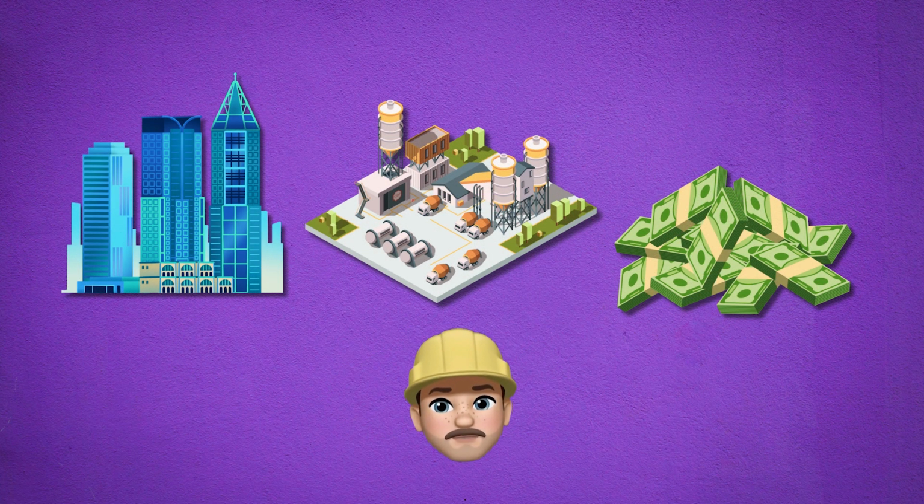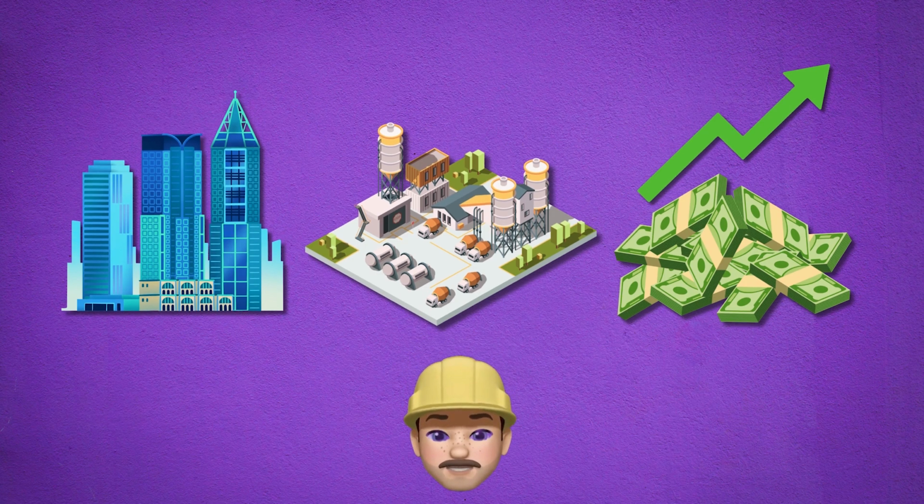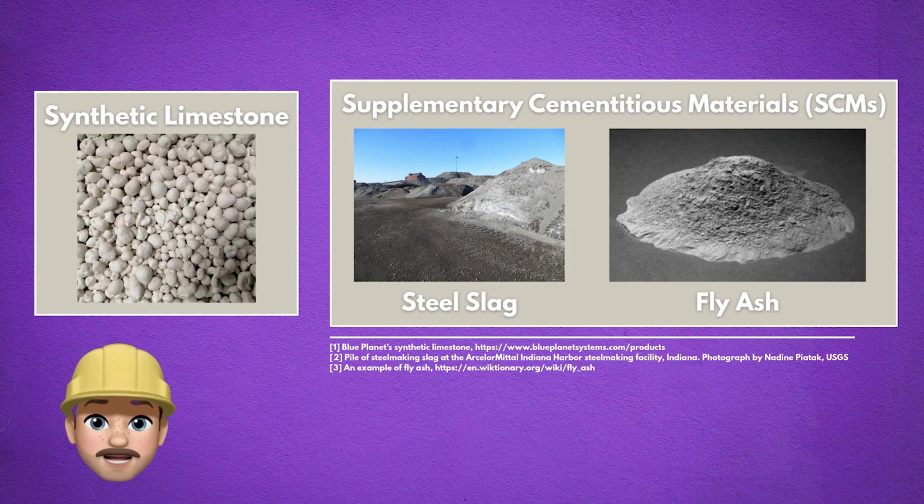Some startup companies are bringing technologies to market that capture carbon dioxide in concrete. Synthetic limestone aggregates, which are 44% carbon dioxide, can replace mined limestone aggregates. And carbon dioxide-infused supplementary cementitious materials, which are based in recycled industrial waste products from the coal and steel industries, can replace the cement. And precast concrete can also be infused with carbon dioxide either in the curing or mixing phases.